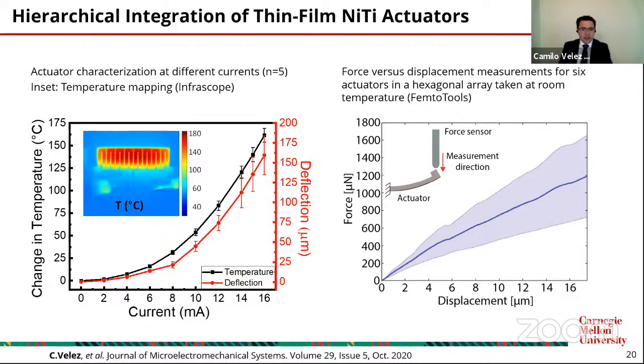If you were going to use very high temperatures, I recommend thinking of a different material, because we found out that it is not only the nickel titanium itself but also the polymer. The polymer cannot sustain more than 225. I think that was the temperature at which we started degrading the polymer. So if you are planning to use high temperatures, we need to engineer the material a little differently. For prototyping it is good, but the polymer needs to withstand higher temperature, and the nickel titanium also needs to have a phase transformation at a higher temperature as well.